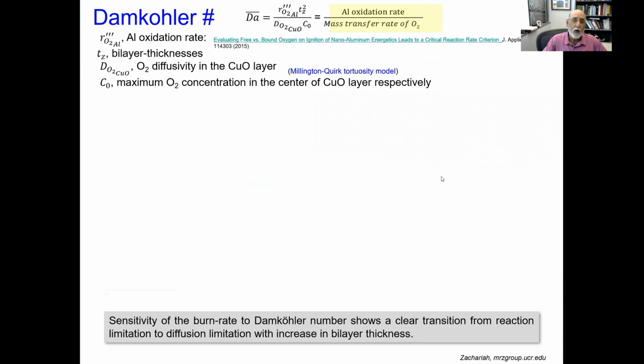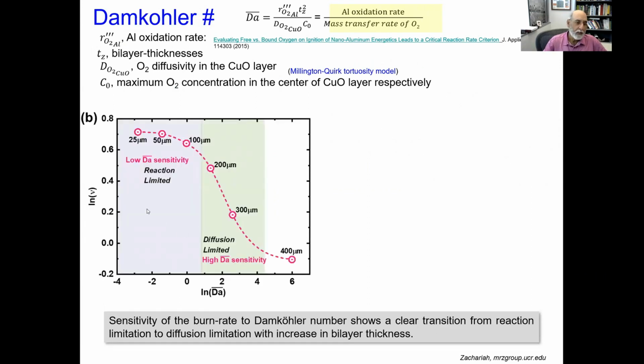This is a Damköhler number, and there are many ways of defining a Damköhler number. This Damköhler number is the reaction rate of aluminum divided by the mass transfer rate of oxygen. And if I take that and I plot the log of the burn rate versus this Damköhler number, and we plotted it this way because the derivative of this is a sensitivity coefficient. You can see that when we're